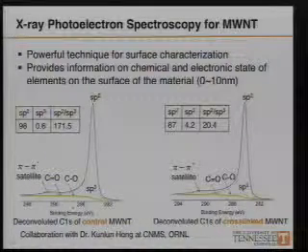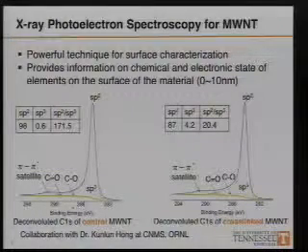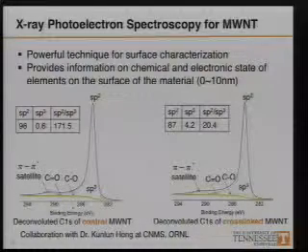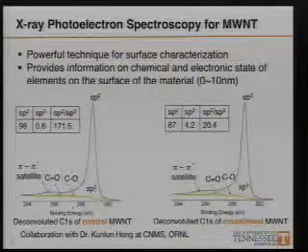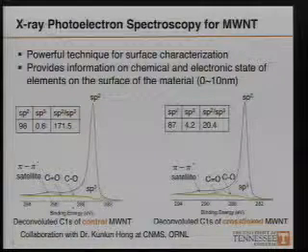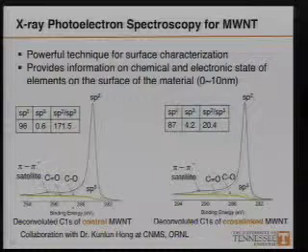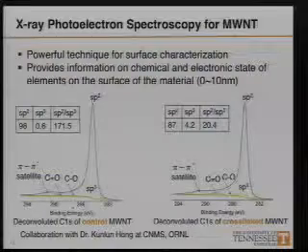After deconvolution, integration, and normalization of these peaks, we can compare the value of sp2 and sp3 hybridized carbons before and after crosslinking. We'll see that sp2 carbons have decreased, while there's an increase in sp3 carbons, indicating that some double bonds on the carbon nanotube have been effectively functionalized and covalently converted into sp3 bonds.